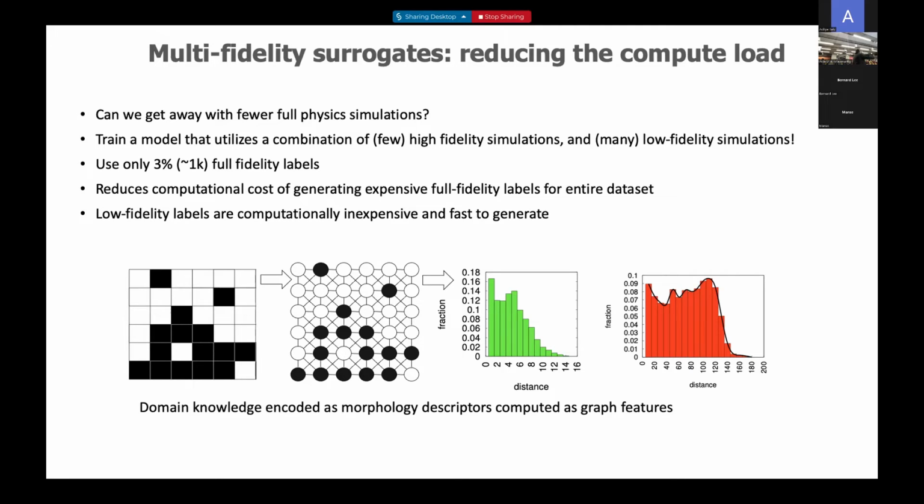The low fidelity framework, worked on by Olga Odu, uses a mechanistic model of the microstructure. If I represent a microstructure as a graph, I can ask a lot of graph queries of it. For example, is a certain domain pixel connected to the bottom, so that there's a pathway for charge transfer? How many islands are there? What is the average distance an electron has to travel to the bottom, or the average distance the hole has to travel to the top, and so on.